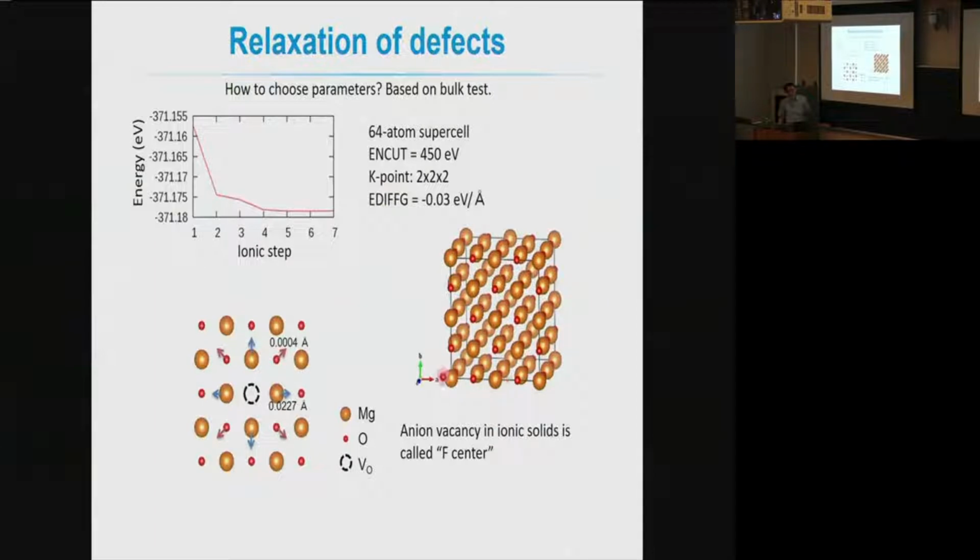And the K-point actually reduces reciprocally with respect to the lattice parameter. That is to say, for the conventional cubic cell, if 4x4x4 K-points was enough, then in this 2x2x2 supercell you reduce the K-point density inversely to the lattice parameter, so you reduce the K-points to 2x2x2. Those are things you check before you start your computation.